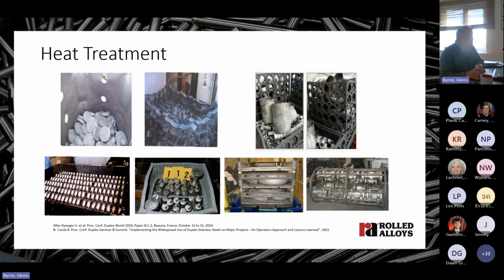Now, the bottom row of photographs show a much better distribution of parts going into the furnace and the use of specialised supports and cradles to allow this. In this case, you can see this specialised basket containing well-spaced large diameter butt weld fittings, and in this case, this cradle is holding valve castings ready for heat treatment.